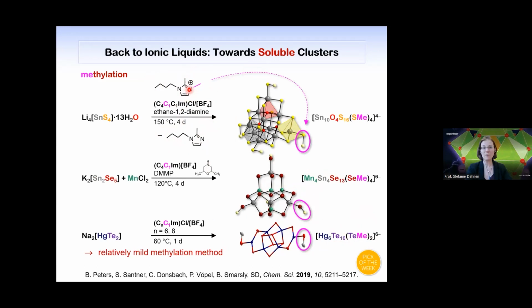So this is a relatively mild methylation method, if you think of things like methyl iodide or methyl triflate, which are really harmful and toxic. And it is interesting to note, it is the only method to post-synthetically alkylate these kinds of clusters. If you take any of the other methods, it will just not work. So there were two good things at once, and we dug further into that because with the methyl groups on it, the cluster is not yet soluble.